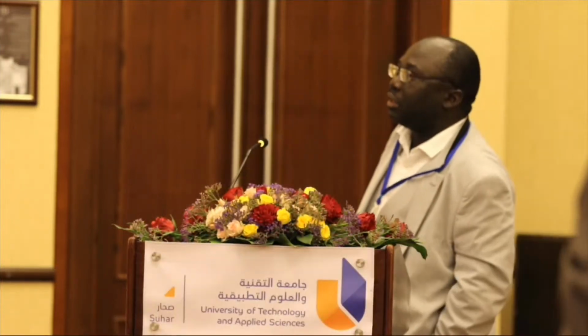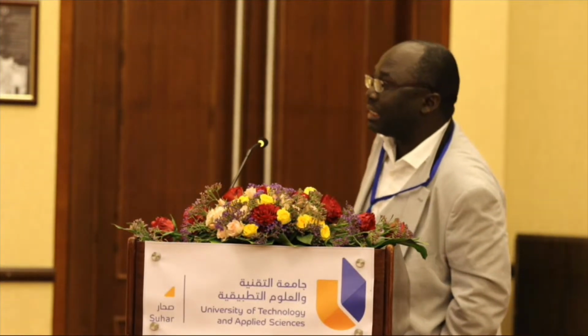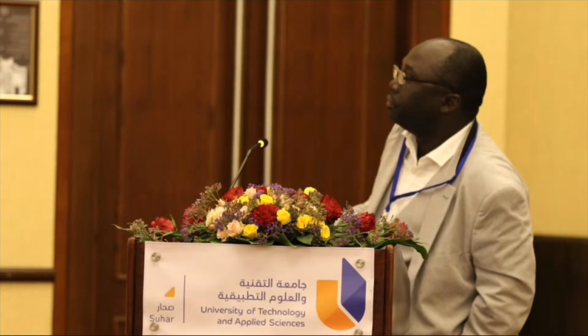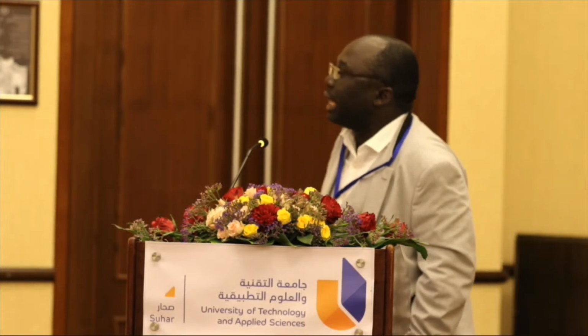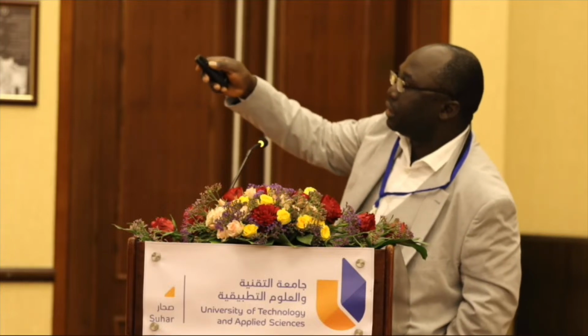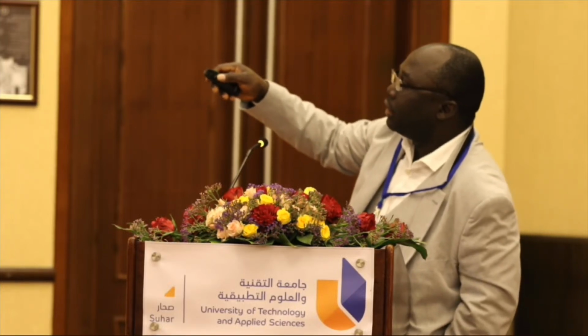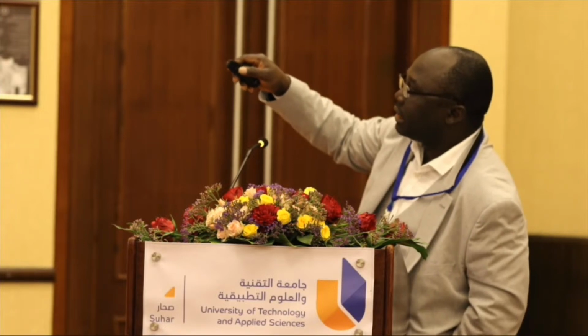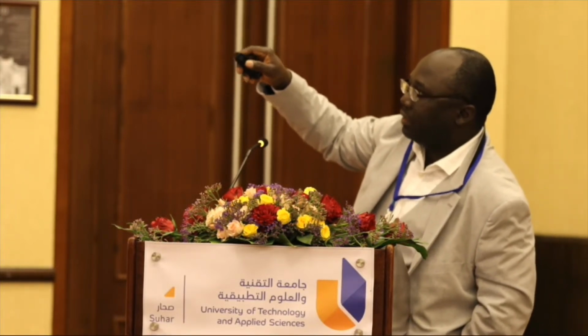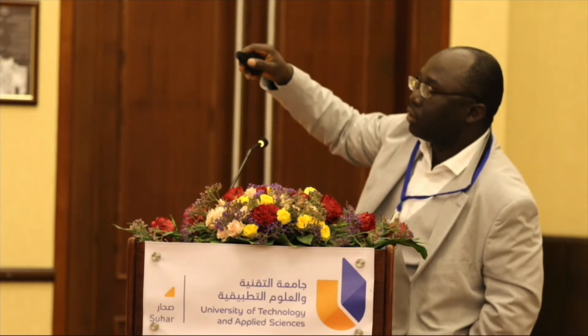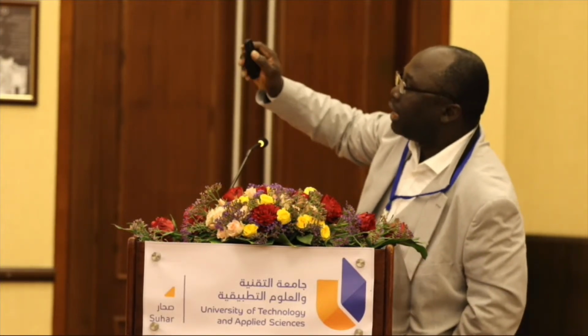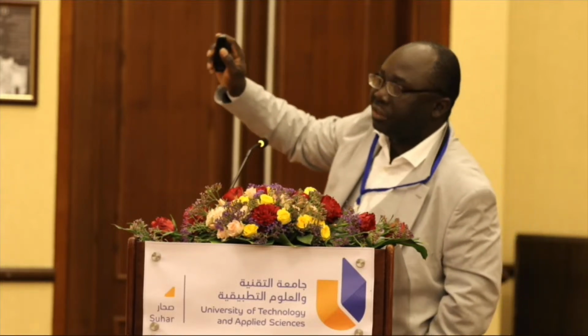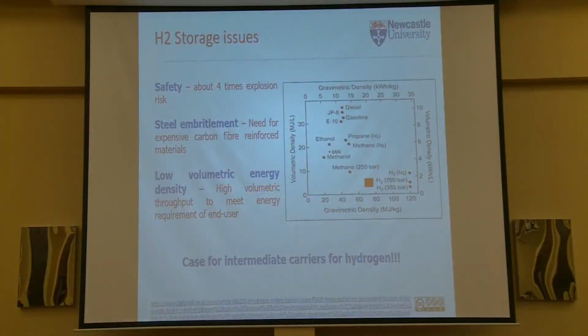Then the other point which I have mentioned is low volumetric energy density for hydrogen. If you look at this figure here, you see that in terms of the gravimetric density, which is on the horizontal axis, the energy density of hydrogen is way higher than that of other common fuels. But where the problem is, is when you are now looking at the volumetric energy density. This is very, very important because this is what you will use to estimate the required volume of storage tanks, for instance, that you will need to transport hydrogen.